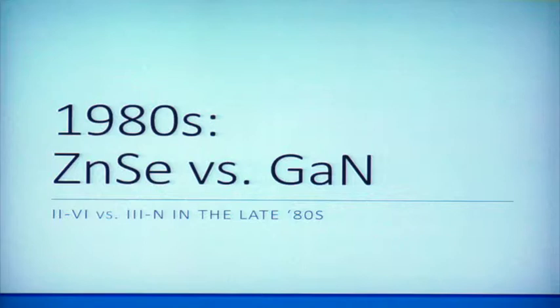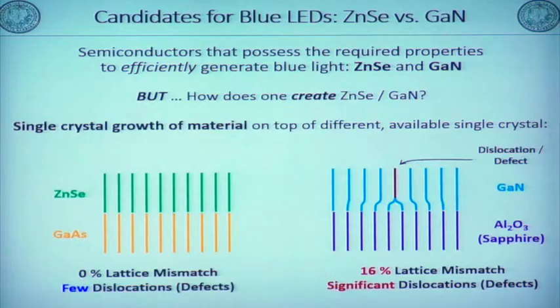So next, I'd like to talk about how I invented the blue LEDs. I started the blue LEDs in '89. At that time, there were 2 kinds of material to develop blue LEDs. One is zinc selenide, and another is gallium nitride based materials. For zinc selenide, there is a good substrate to grow it, called gallium arsenide. So gallium arsenide substrate could be used to grow zinc selenide, with no lattice mismatch.